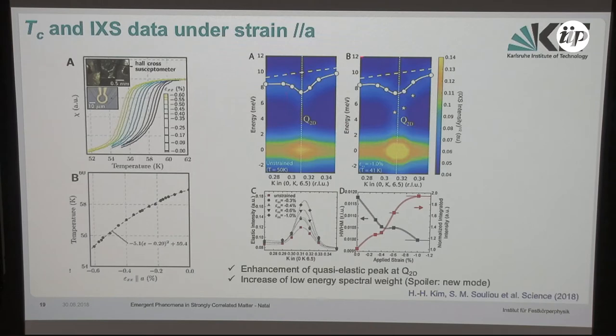So here's my Kohn anomaly in the absence of pressure. And if I apply uniaxial pressure, you see that there is a clear enhancement of the elastic line. I mean, the intensity almost doubled with 1% compression. And if I look at this color map here, you see that there is some extra spectral weight. So we first thought that the softening was somewhat enhanced. But what we found out is that actually it is another mode that is getting softer.